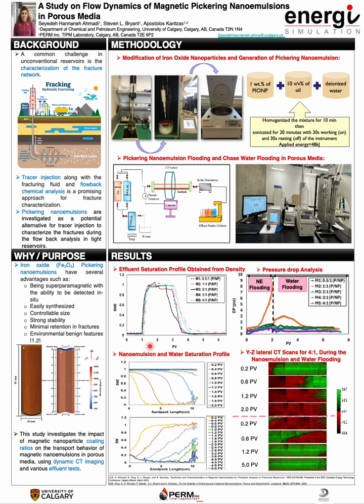For all the experiments, I mean the different ratios like 0.5 to 1, 1 to 1, 2 to 1, 3 to 1, and 4 to 1, I named them M1, M2, M3, M4, and M5. Initially saturated with water, the sandpack gradually experienced invasion by the nanoemulsion. During nanoemulsion injection, water production was observed until the breakthrough of nanodroplets, which occurred at approximately 1 pore volume for all experiments. The subsequent increase in the saturation profile indicated nanoemulsion breakthrough.